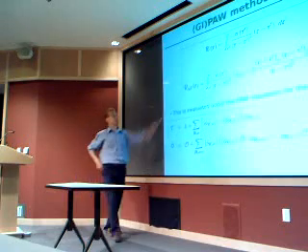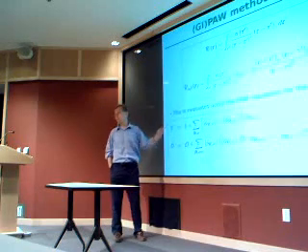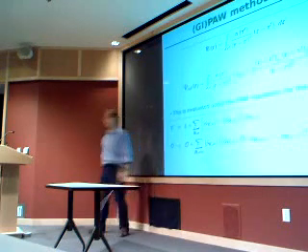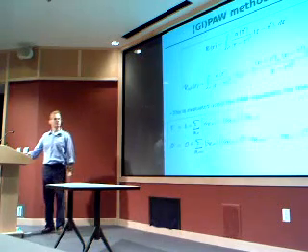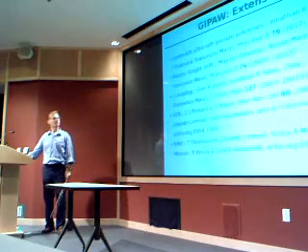If you remember, you have to do the linear response in the case of chemical shielding. Here you just need to reconstruct the density, use this formula, and you get the matrix. So usually this takes a couple of seconds, even for bigger systems, whereas the calculation of the chemical shielding can take quite easily days, even on large computers.